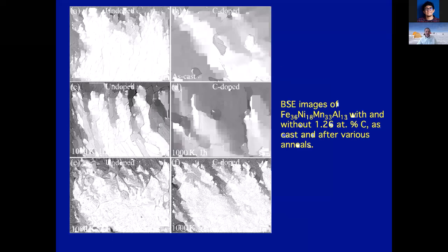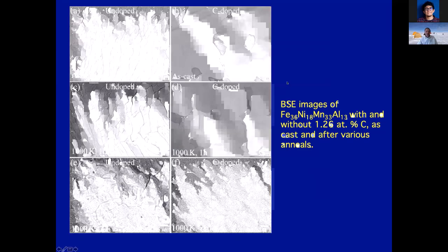So we also looked at adding carbon to this material because carbon turned out to be a really great strengthener for that single phase alloy. Interestingly, when we added carbon to this material, a completely different thing happened. So this is the undoped material where we've got these lamellar structures. Once we added carbon, we completely did away with the lamellar structure, and we got these islands of precipitates in the material. When we annealed both the undoped and the carbon doped, eventually what we got was this precipitation of this second phase that you saw before.